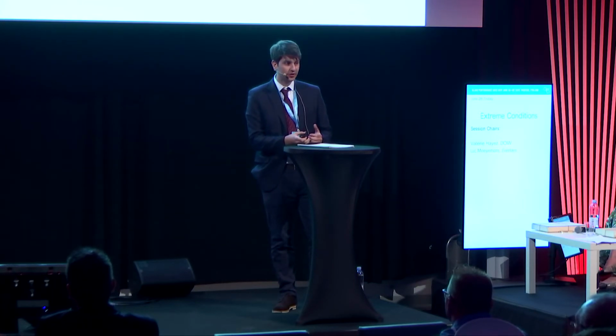In this case, we have assumed the same collapse mechanism as for simply supported beams, also for the axially restrained case. This is a common assumption that is considered in the plastic analysis. However, this means that all the plastic bending and membrane strains will be localized at the plastic hinge length. However, as the deflections keep increasing, the plastic hinge length will also extend and eventually reach the entire panel, entire beam length, when we have a pure membrane response.